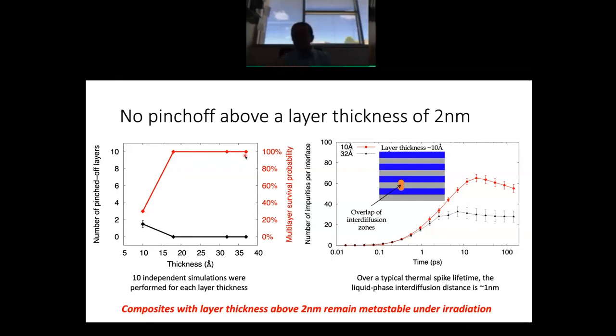Why is that? The reason for that is because, doing some very simple calculations, we can show that the pinch-off events, when they occur, happen because interdiffusion zones from two neighboring interfaces are beginning to overlap. So if you were to look at a typical thermal spike lifetime and compute the liquid phase interdiffusion distance, it's about a nanometer, okay? So if you have a layer thickness that's a nanometer, 10 angstroms, that means that two interdiffusion zones from neighboring interfaces can overlap. That's how you get the pinch-offs. If you have any layer thickness that's larger than that, you will still get those interdiffusion zones, but they're not going to be big enough to overlap.